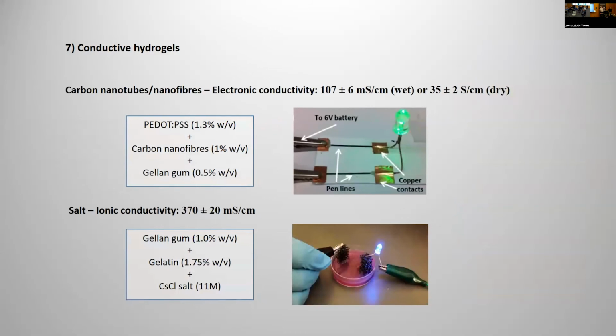Okay, and I think this is one of the last ones. I can't remember how many numbers I put in, but number 7, conductive hydrogels. So you can make conductive hydrogels using 2 different methods. One is electronically, by putting things such as carbon nanofibers, graphene, actual metal particles, whatever you're putting in there. Or you can simply go with salt. So ionic conductivity, we found, was actually 3 times or more than 3 times higher when it's in a wet gel. So something to keep in mind when you're making your graphene hydrogels. It's sometimes easier just to chuck a bunch of salt in there.